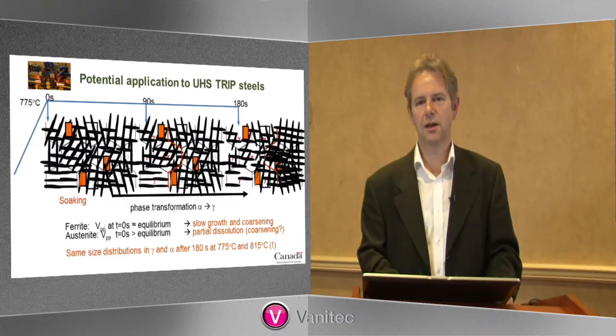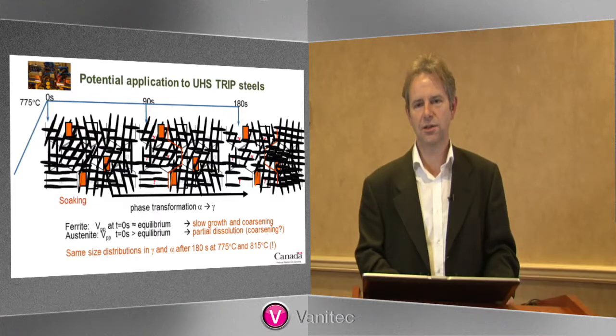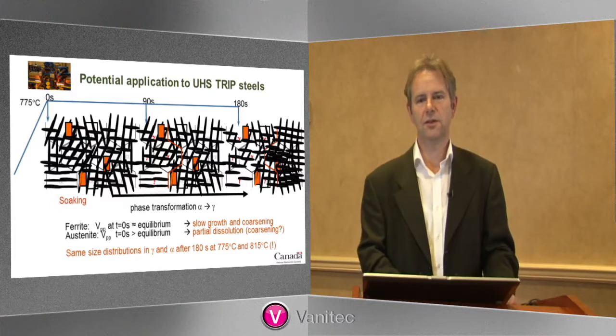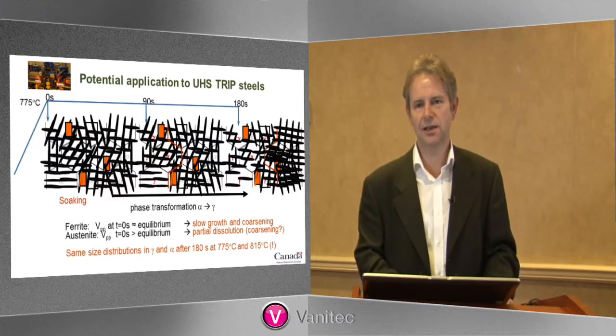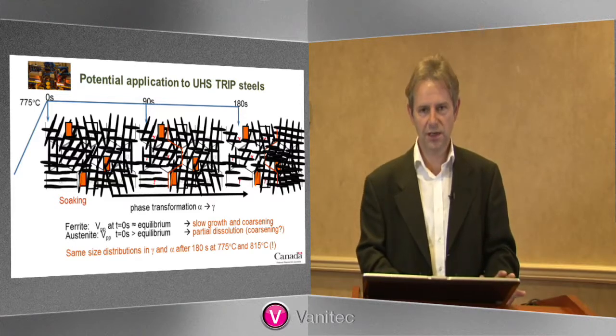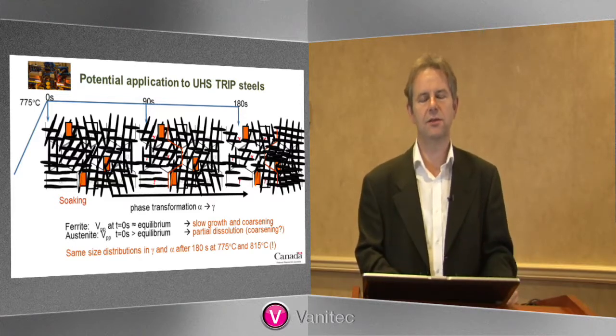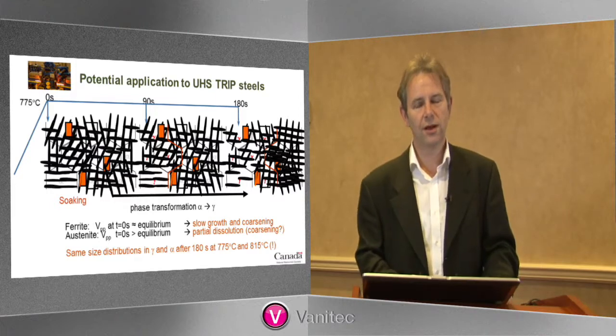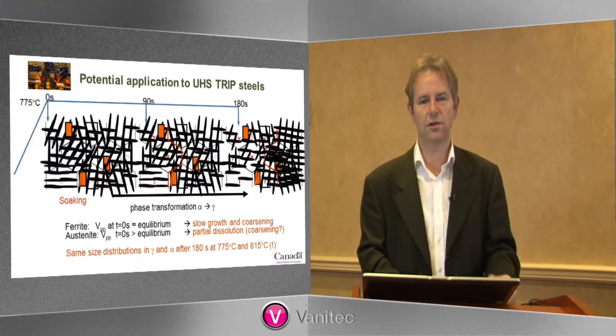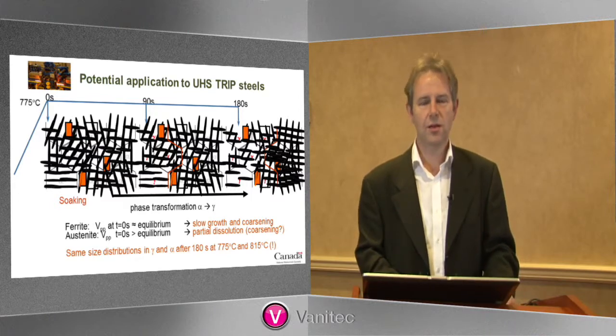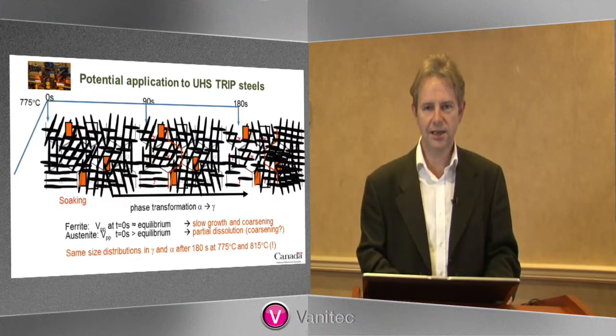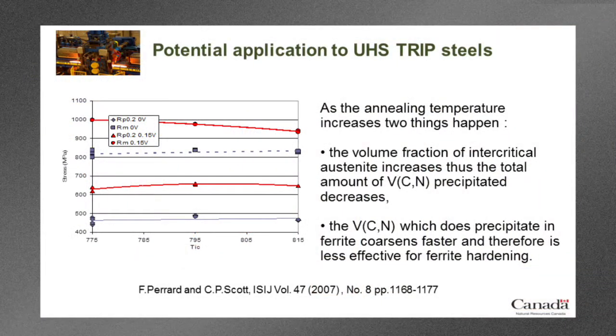So this final distribution at the end is what we would expect. We have very few fairly large precipitates in the austenite and a high density of precipitates in the ferrite. And it turns out, interestingly enough, that the mean radius in this phase and in this phase is actually the same. We can't really explain that at the moment. It's a very complicated phenomenon that we'll have to couple phase transformation modeling with precipitation kinetic modeling. And that work is actually ongoing at the moment. But the important point is that we have selectively strengthened this ferrite phase. So to come back to our original question, why do we see these differences in mechanical properties at the lower annealing temperature compared to the higher annealing temperature?